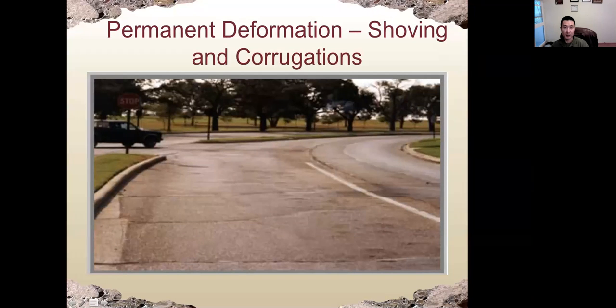All right, and here we have another type of deformation. It's called shoving or corrugation. As probably you can see here, we have a stop sign. Because at a stop sign, the vehicle often does stop and moving. This stop and moving motion will cause asphalt to crack. And the crack will be patterns like this. The direction of the crack will be perpendicular to the direction of the pavement. The reason for that is because the asphalt is too soft, or we have too much moisture underneath the pavement.